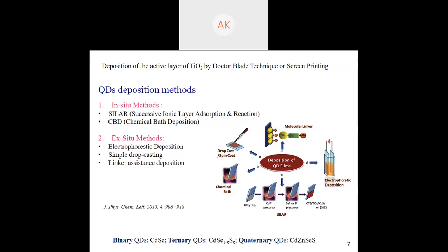I'll tell you an example. Suppose you take indium acetate in a beaker, you take a sulfur precursor, maybe any kind of sulfur precursor, maybe thioacetamide, and you put it inside the beaker. You add water, you put it at 70 degrees over a stirrer. You keep your films immersed in the beaker. Now, as the reaction goes on for maybe 1 hour, 2 hours, you see the indium sulfide forming over the TiO2.